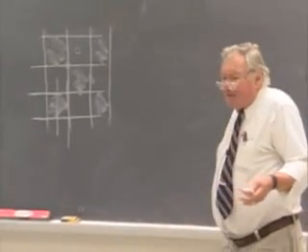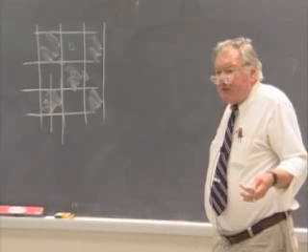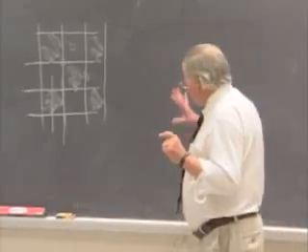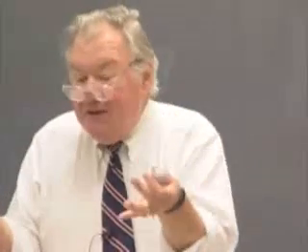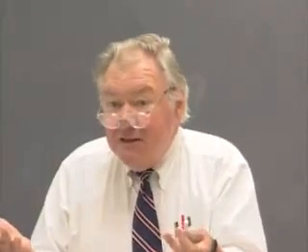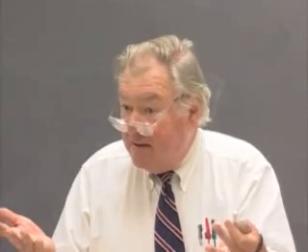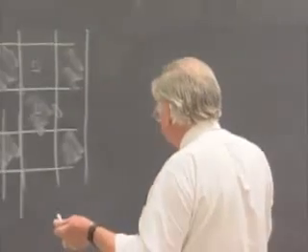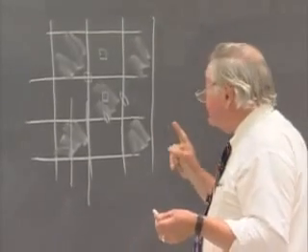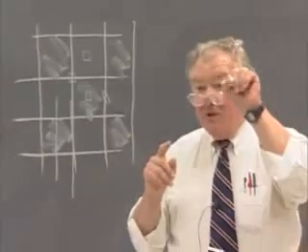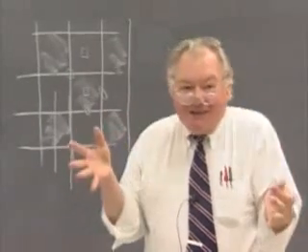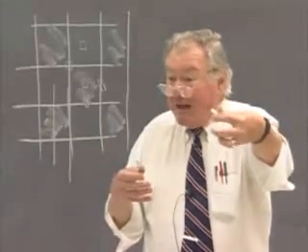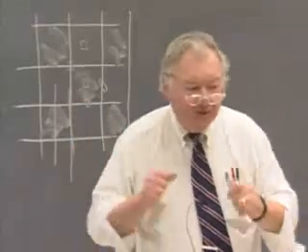Does this have any utility in the physical sciences? Be nice for wallpaper designers, but does it have utility in physical sciences? And the answer is yes, because what is going on here is that there is a binary character assigned to each of the motifs. So anytime the atom or whatever you have, the molecule, has some sort of binary characteristic that it can exist in 2 distinct states, the arrangement of that sort of motif requires a black-white symmetry. And one example in crystals that requires this sort of symmetry is the case of a magnetic structure, and I think I mentioned this last time, where the magnetic moment can either point up or down. Well, saying that you have an atom with spin up and an atom with spin down is the same thing as saying, in terms of transformations, having a black atom or a white atom. It's a binary character that switches from atom to atom.